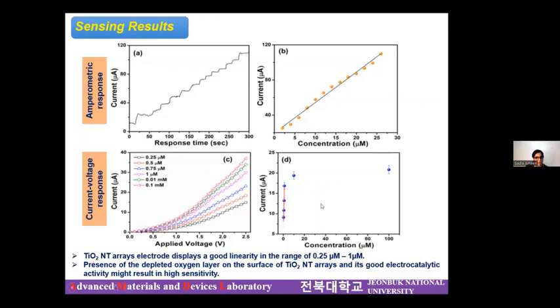From this figure you can see that it shows good linearity in the range of 0.25 micromolar to 1 micromolar. After that, it has become stagnant. The reason for getting the stagnant response might be the lack of active sites over the surface of the electrode material.